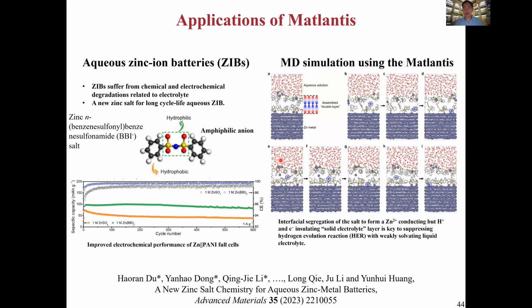But it actually is hydrophobic and it's not allowing the proton to contact the zinc metal. And that is the key insight, which is you need to have this, quote unquote, electron insulating, so electrons cannot tunnel, and also proton-phobic self-assembled layer, which nonetheless is still a good zinc solid electrolyte.